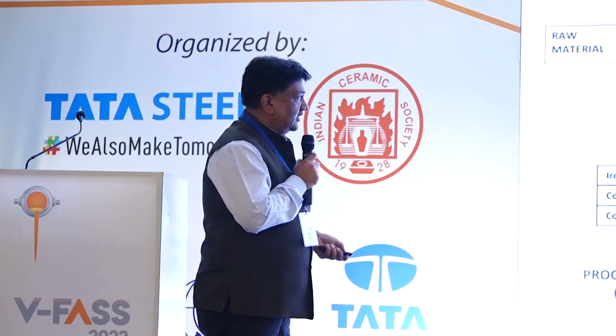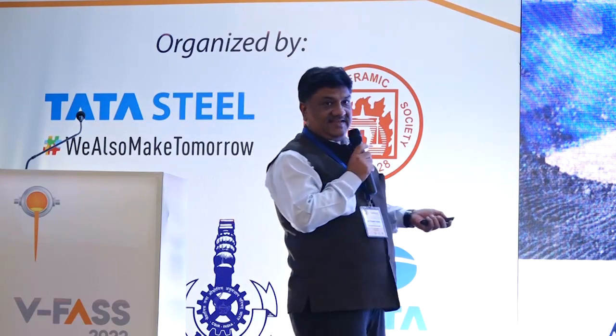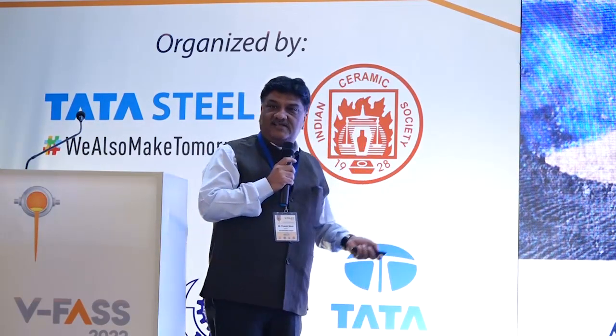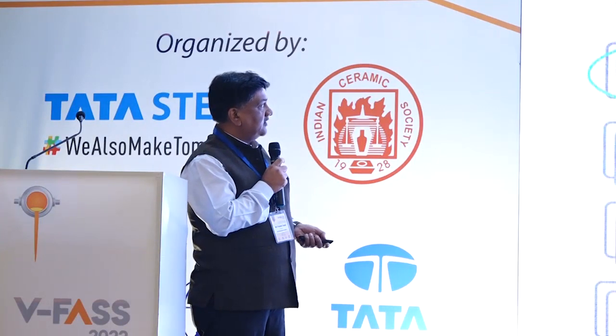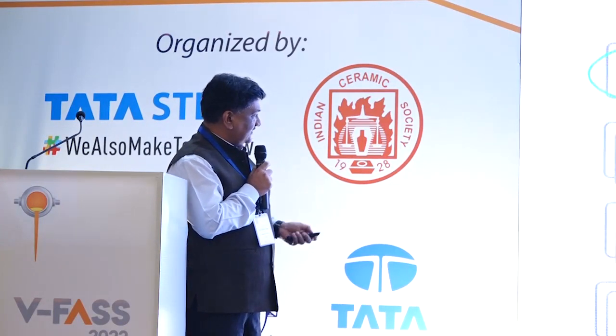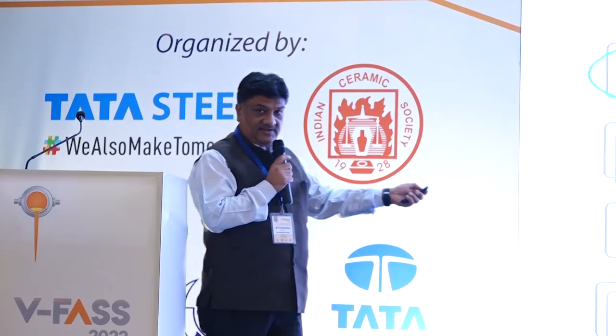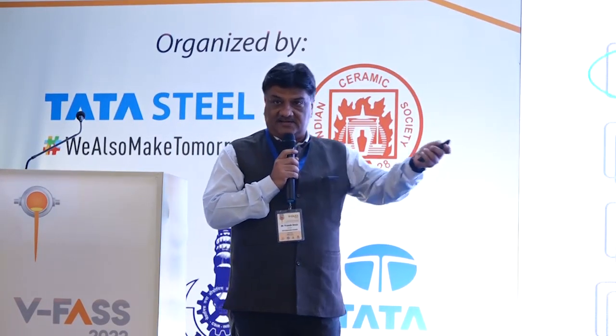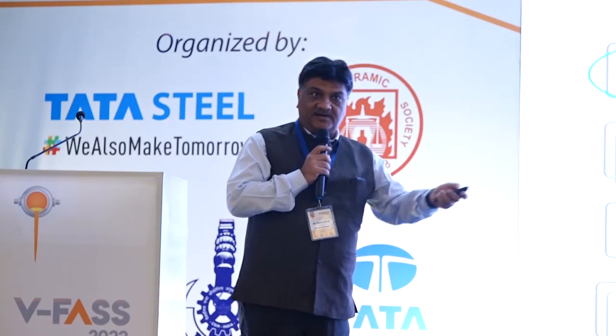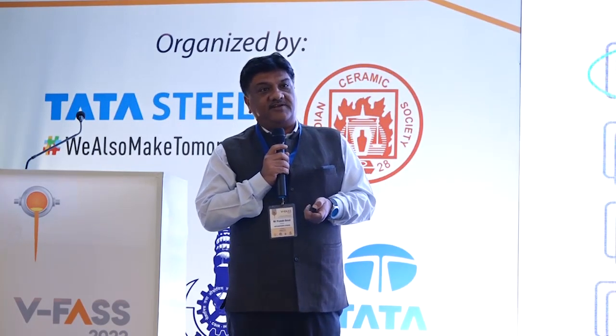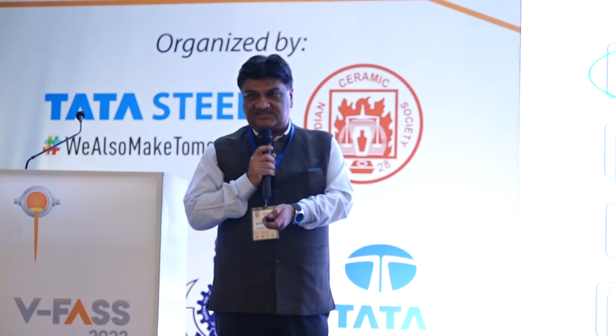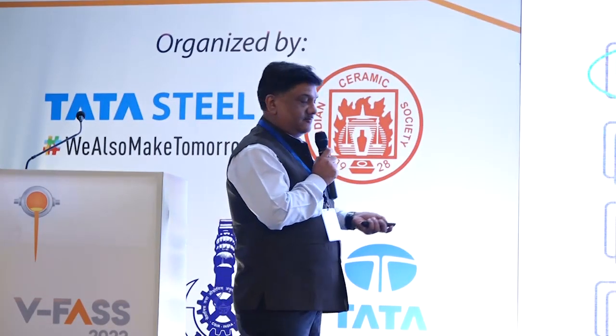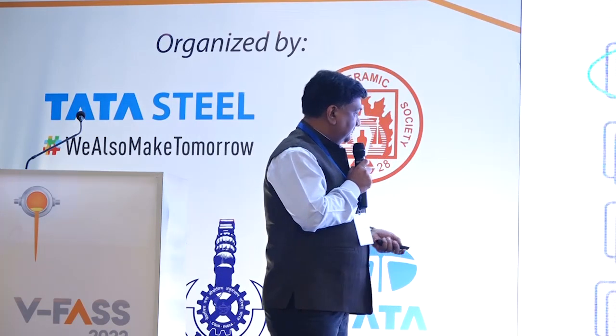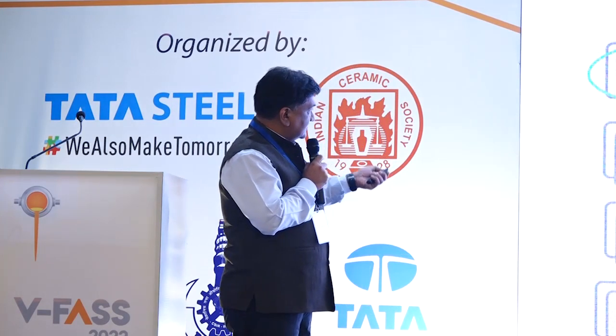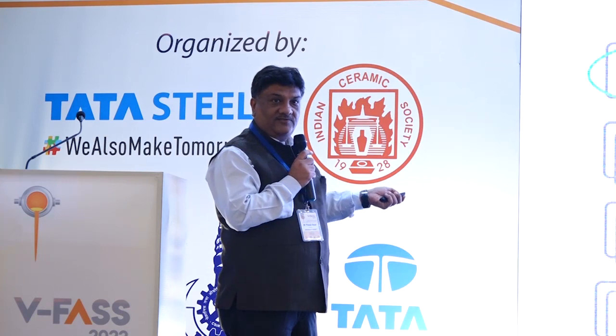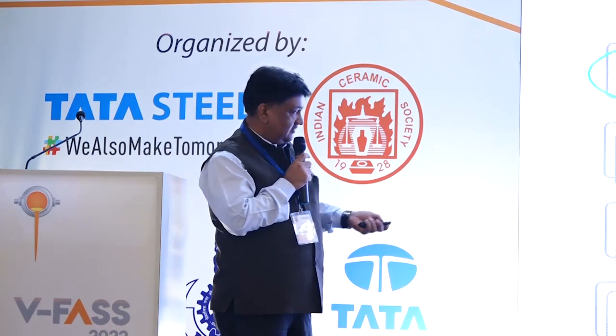So we tried to experiment with these slags, and we asked what could be the application areas using such products. We know the BF slag, and it has been used in cement. We are producing this slag cement at our Jamshedpur cement plant at 50 to 70%. Professor Manu Santhanam was saying we are actually using 65 to 67% of slag for one of our products. And of course, my attention today will be on the ACBF slag aggregate, what we have done.